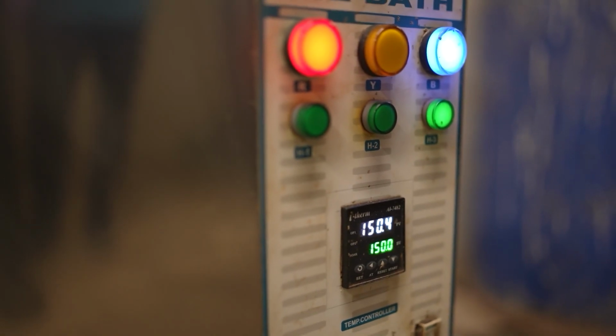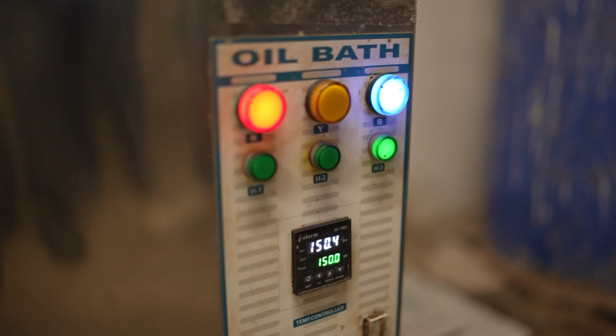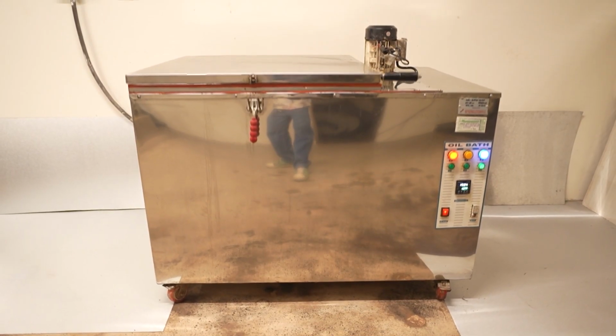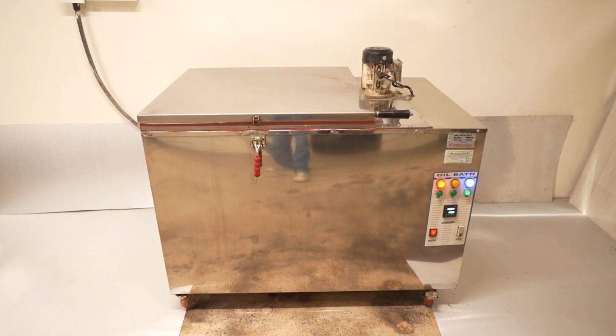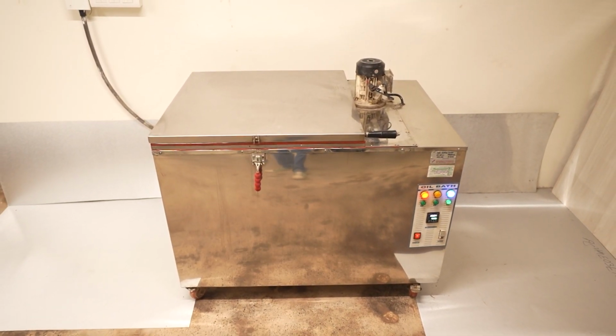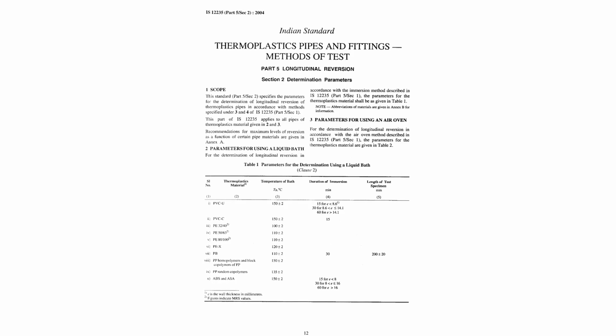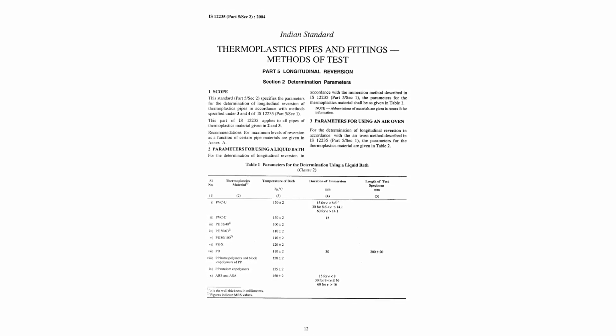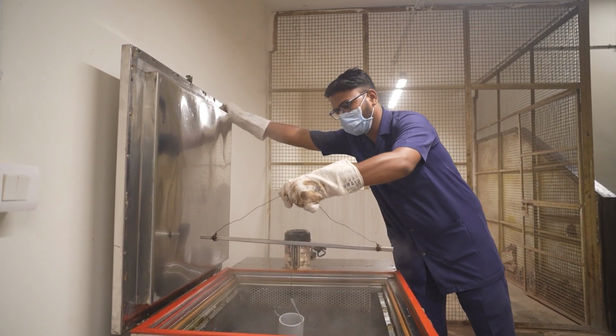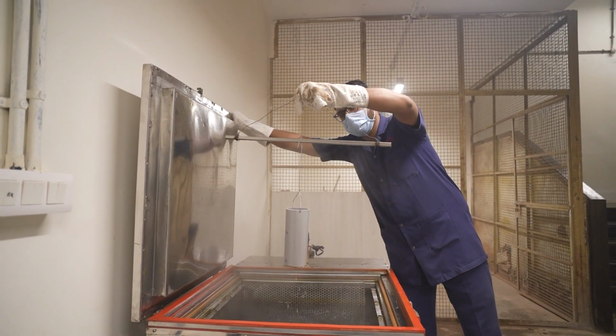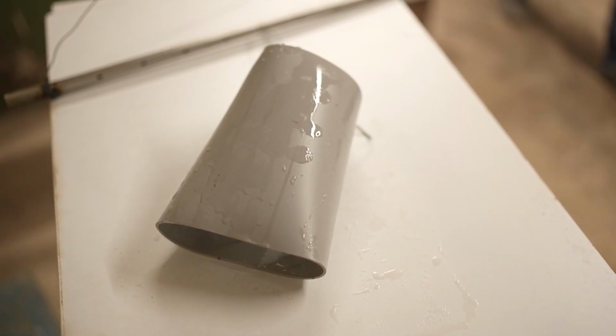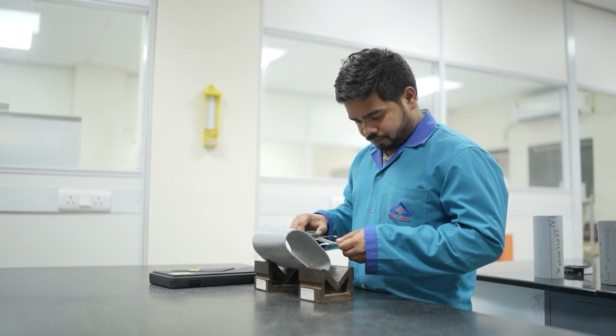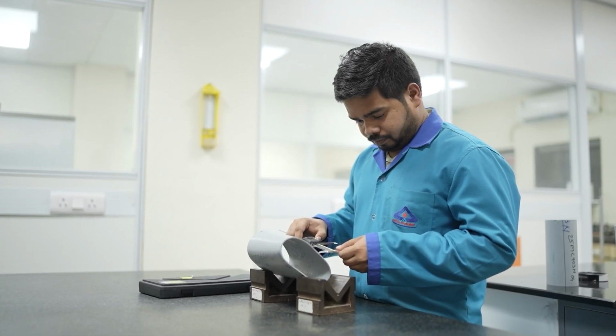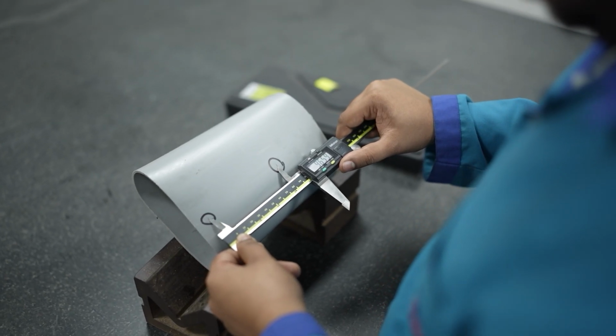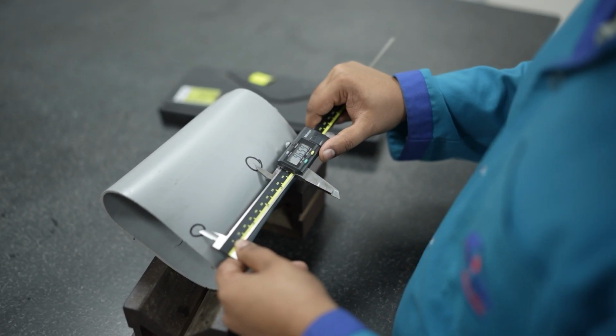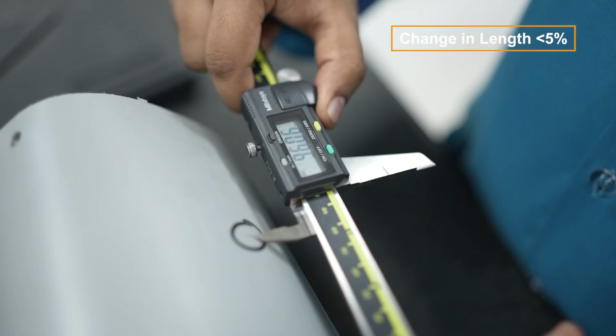The temperature is maintained at 150 plus or minus 2 degrees Celsius. The specimen is allowed to remain in the bath for the designated duration as outlined in the standard. The time duration depends on the wall thickness of the specimen. Once the immersion time is complete, the specimen is carefully removed from the bath and allowed to cool to room temperature. After cooling, the distance between the 2 scribed marks is measured, and the percentage change in length is calculated. The length shall not alter by more than 5%.